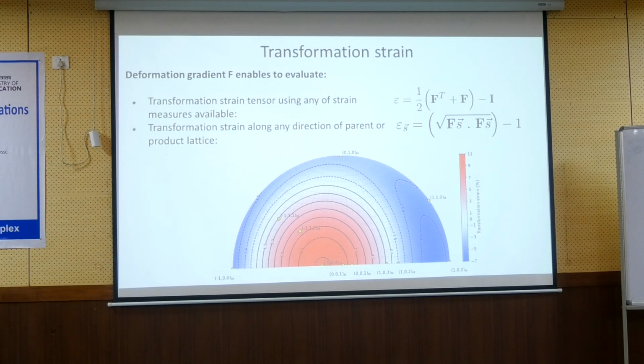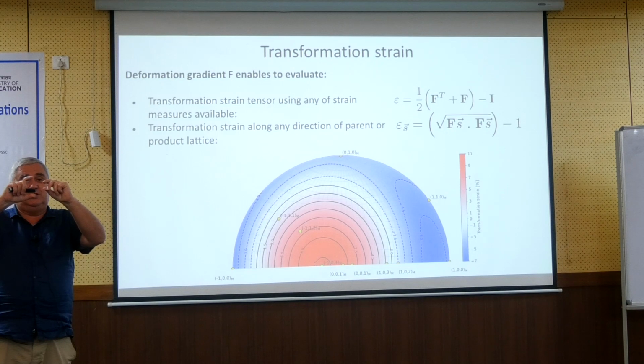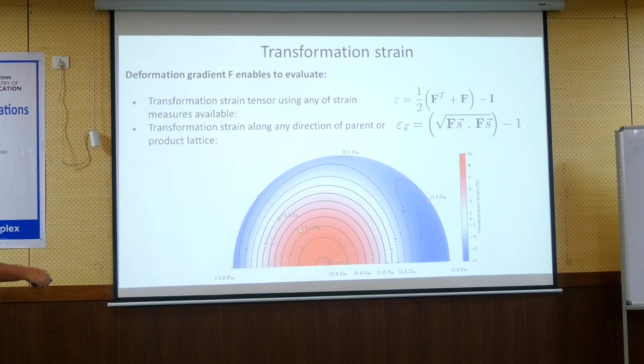And if you have this, well, okay, you even don't need. This is the calculation, as I said before, if austenite changes to the martensite, so I can calculate in which direction I would have which strain. So this is the calculation in monoclinic lattice, which says that the major elongation is around the -103 direction. So, remember only this simple fact that you have austenite and you have martensite, and martensite is long in one direction, and this is -103, and this gives such kind of orientation dependence.